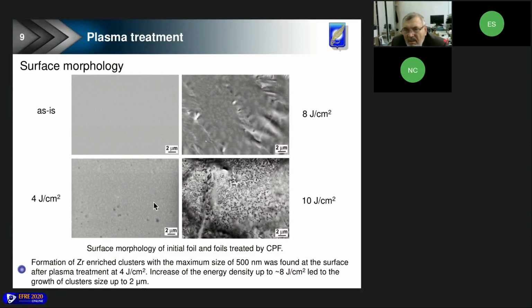Here you can see that after plasma treatment at 4 joule per square centimeter, formation of clusters with a maximum size of approximately 500 nanometers was found on the surface. Due to elemental contrast formed by backscattered electrons, they appear as bright areas, so these clusters had higher atomic density or contained heavier elements. So one could suppose that these clusters should be zirconium enriched as compared to the other metals. Cluster formation indicated the beginning of disordered structure disintegration, in spite of the fact that crystalline phases were not found in the diffraction pattern.